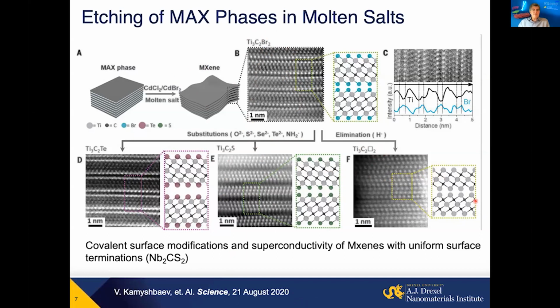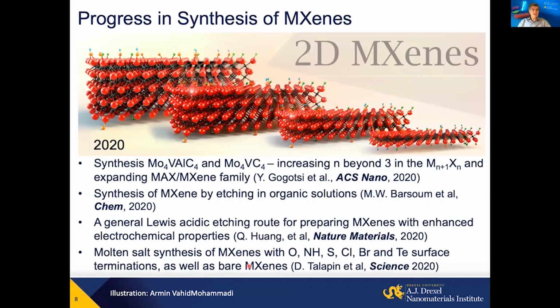You can only imagine what a variety of properties can be achieved, for example, by making sulfur termination instead of oxygen on the surface of niobium carbide. They demonstrated superconductivity in those materials. And the discoveries keep coming. Just in 2020, and we are only in September now, we showed an additional group of MXenes with 5 layers of transition metals.